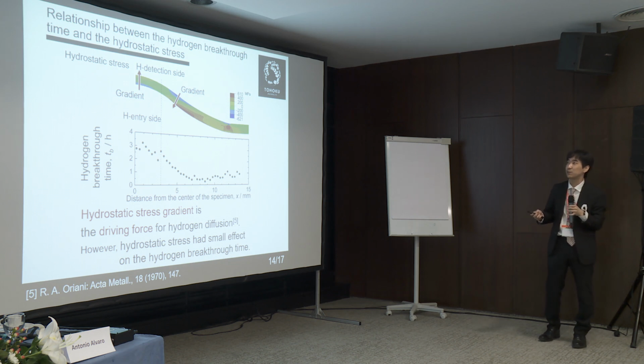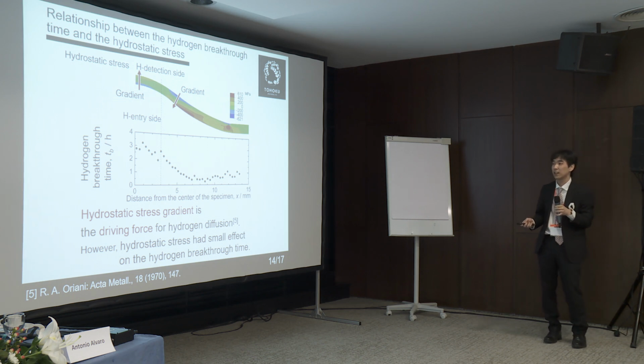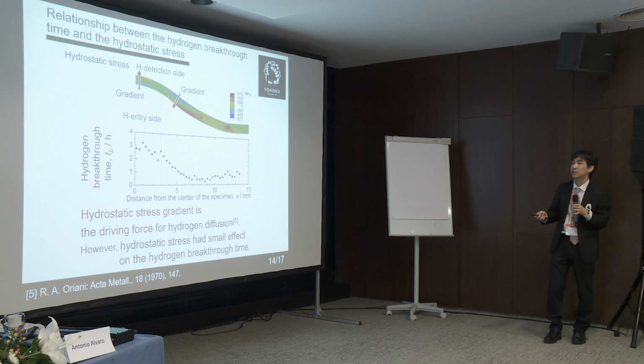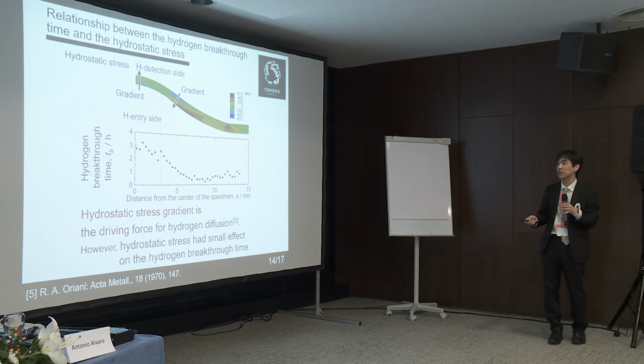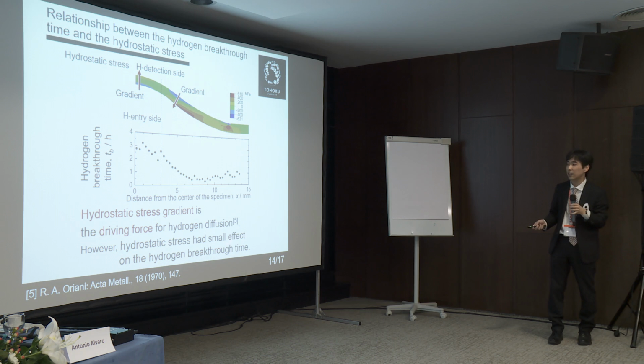This is the relationship between the hydrogen breakthrough time and the hydrostatic stress. It is reported that the hydrostatic stress gradient is the driving force for hydrogen diffusion. For example, hydrogen diffusion will be accelerated in this area and retarded in this area. However, the hydrogen breakthrough time was long around the center. So we can say that hydrostatic stress has a small effect on the hydrogen breakthrough time.